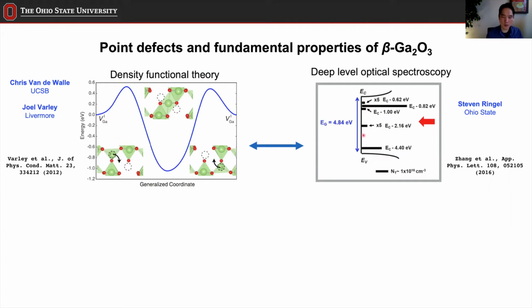And then one popular way of measuring the defect trap state is using deep level optical spectroscopy, and that's done by our collaborator Steve Ringel at OSU. So what they do is they measure the defect trap state in between the band gap. If you look at the band gap, obviously if you have no doping or anything, you expect nothing showing up in between. There shouldn't be anything between the conduction and valence band, but you get a lot of stuff here, right? The length of the bar represents the concentration, and that's the corresponding energy, meaning that something is there in the structure causing these trap states.